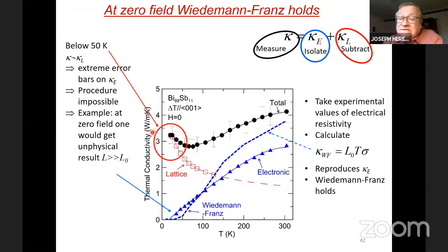Now, let me point out one experimental difficulty we have at low temperature. Below 50 Kelvin, the error bars on thermal conductivity are here. The lattice is here. So the difference between lattice and total is really within the error bar. So when we make that subtraction between the total and the lattice, we end up with an electronic, but it is imbued with a very large error bar. And of course, below 50 Kelvin, that error bar becomes so large, there's just no way we have accuracy on the determination of the electronic thermal conductivity. So verifying the Wiedemann-Franz law is impossible below 50 Kelvin.